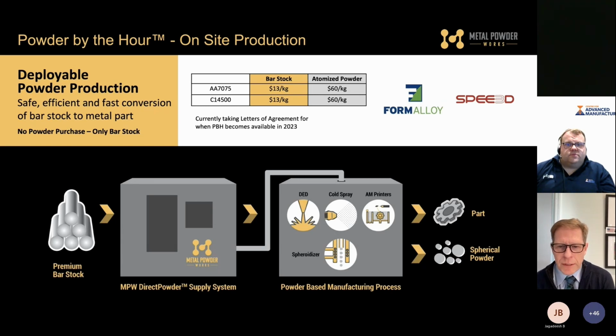Whether that goes into a DED machine, cold spray, or other printers, or is feeding a spheroidizer, at some level we don't care. We can match to the input that's necessary. So theoretically you can now have powder production going from bar stock in to part or spherical powder out, effectively in a very linear and continuous process. We have signed a couple of cooperation agreements with Speed 3D and Formalloy around this concept. With those machines, not exclusive, you could sit our powder generator next to it and feed it on a continuous basis.